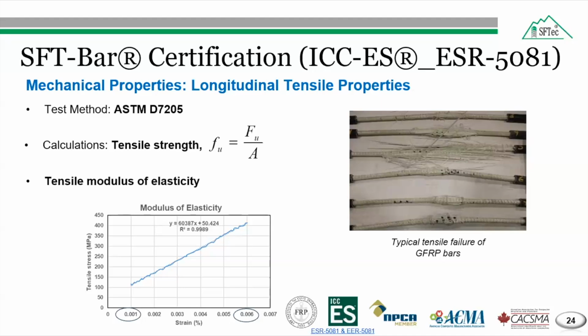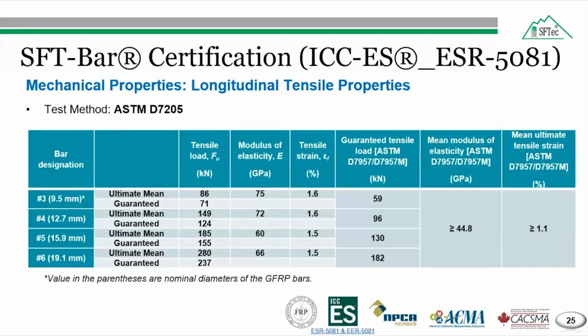The tensile modulus was calculated by fitting a straight line to the data using the method of linear least square regression analysis. The strain range selected for the fitting line was within the lower half of the stress strain curve, with the starting point at a strain of 1000 microstrain and end point being 6000 microstrain. For the helical wrap glass fiber reinforced polymer bars, the guaranteed tensile properties were greater than the requirement in ASTM D7957. And here the guaranteed properties means the mean tensile load minus 3 times the standard deviation.